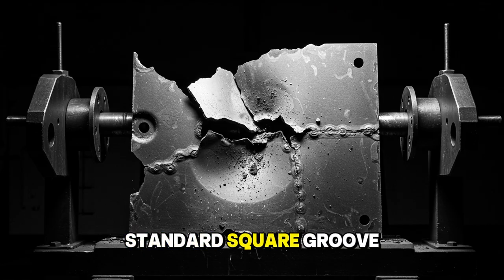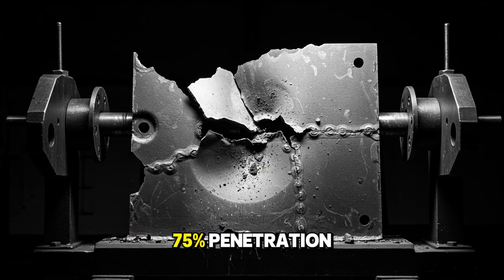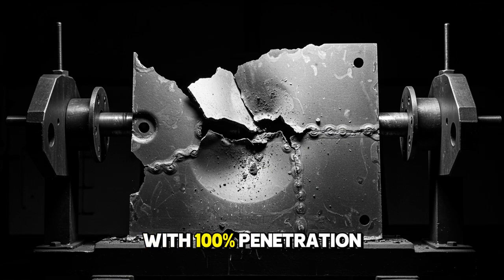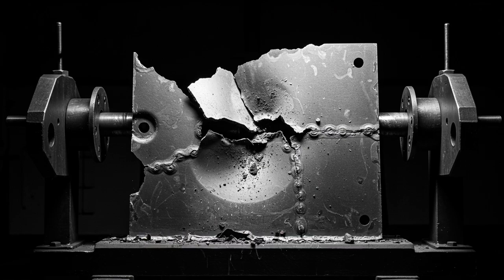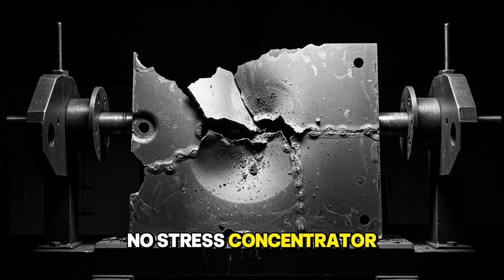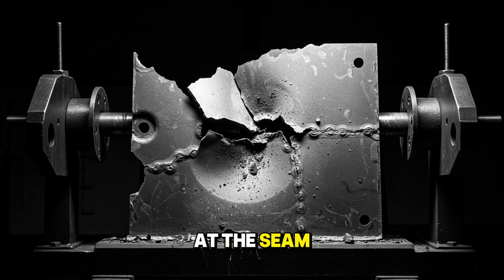Instead of the standard square groove butt weld with 75% penetration, he'd use a double V groove joint with 100% penetration from both sides. Cut a beveled groove into each plate edge, weld from the outside, flip the section, grind out the root, and weld from the inside. Complete fusion. No gap, no stress concentrator. The 2 plates would essentially become one piece of metal at the seam.